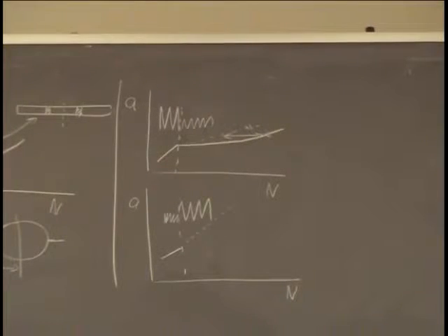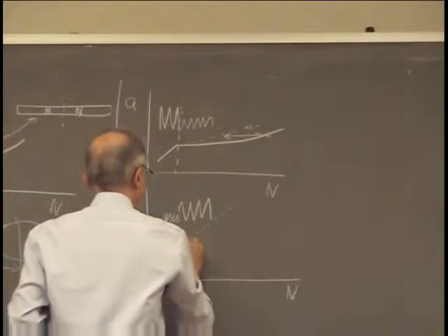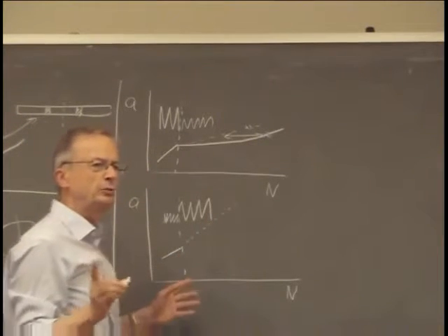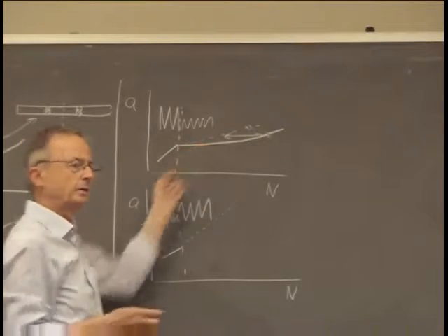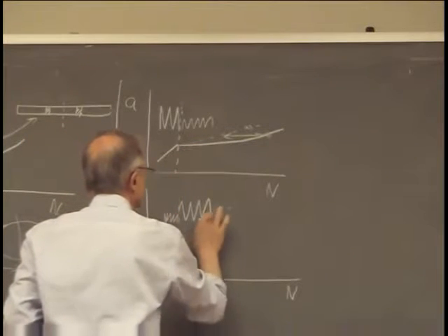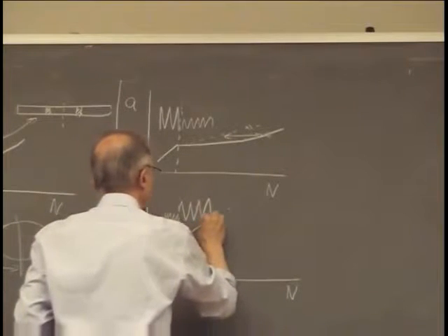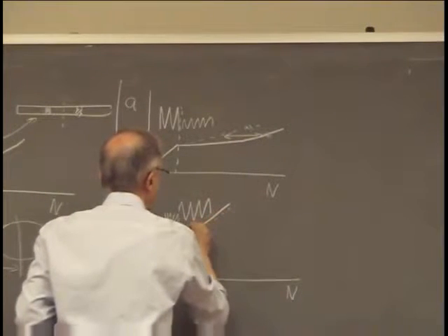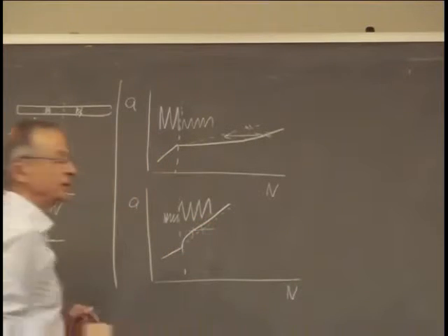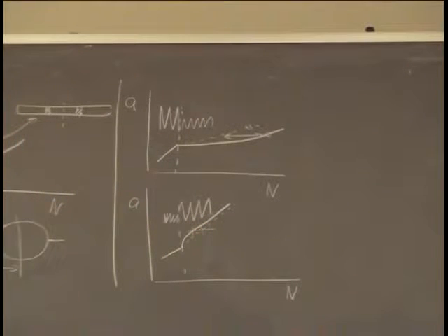What we expect, but it's something that doesn't happen. And we have an acceleration effect, but the acceleration effect is much smaller than the delay effect. So we have something, always getting messy here. We have something that looks like this. And this is the acceleration effect. So there's obviously an interesting history effect.